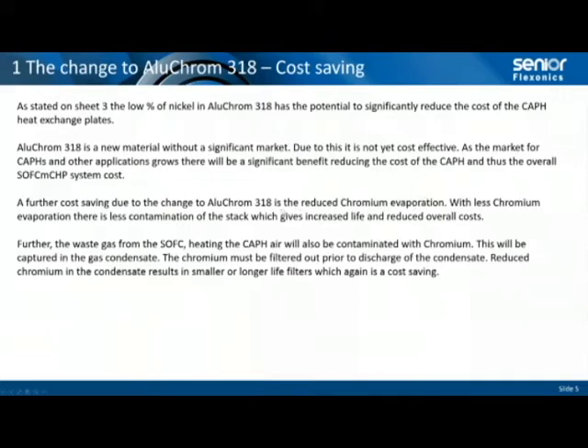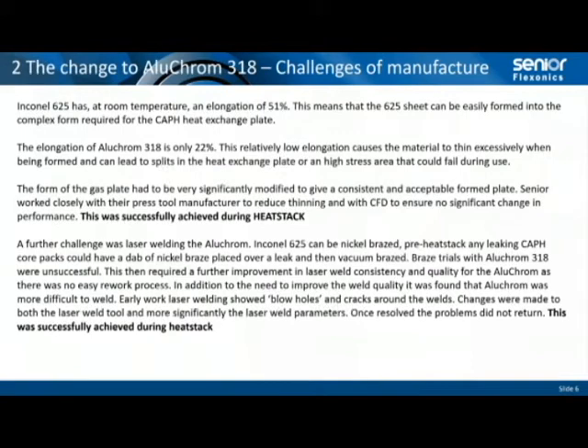Of course, a further cost saving with the 318 is reduced chromium evaporation, and with less chromium evaporation, there's less contamination of the stack, which gives it increased life and reduced overall cost. And also, because we're not contaminating the exhaust gas, which then forms condensate when further cooled, it allows Sunfire to reduce the size of the filters or have longer life filters. So again, a cost saving. So it's a significant advantage with the use of AluChrom.